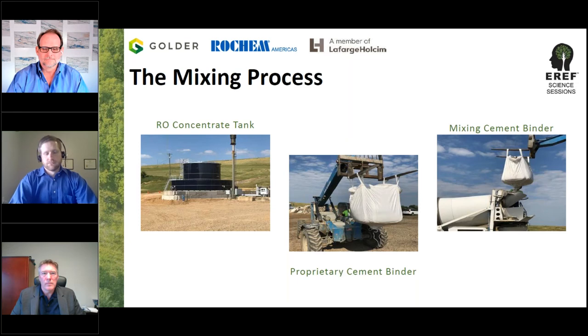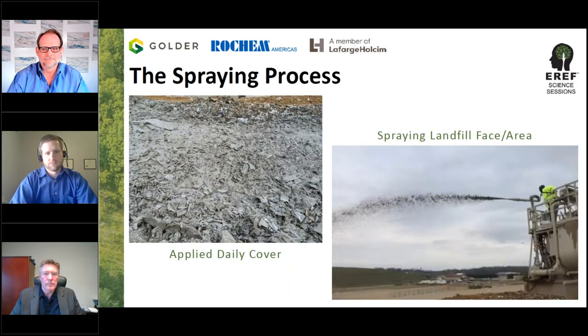A proportional amount of RO concentrate was also loaded into that ready mix truck. Ready mix trucks are really good at homogenizing whatever's inside of them, so what was going on inside the truck was a really good blend of binder and the RO concentrate. If you go to the next slide, you can see where the ready mix truck discharged the slurry into the spray truck that you see on the right. The slurry being sprayed on, all of that liquid is RO concentrate, and on the left-hand side, you can see it being applied as an alternate daily cover.